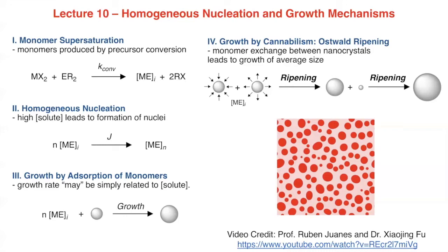And we talked about nucleation kinetics last time and classical pictures about them and how they depend on the surface tension. And then once crystals are formed that are larger than the barrier to nucleation, those crystals can consume solutes. So solutes then have a choice of either forming a new crystal or attaching to an existing crystal.